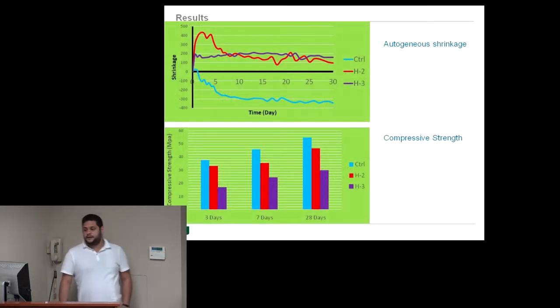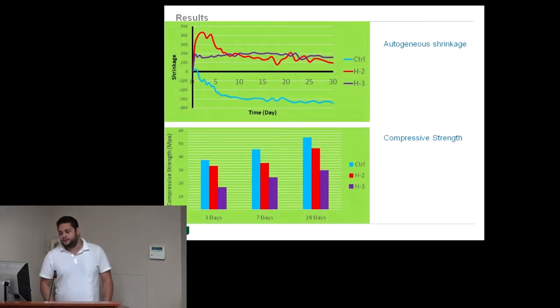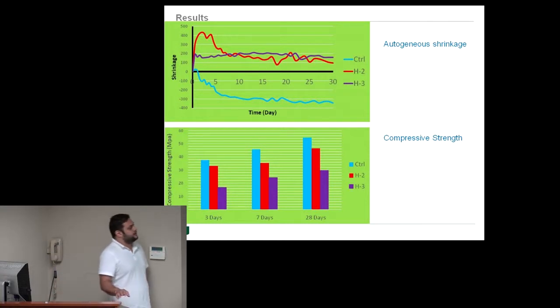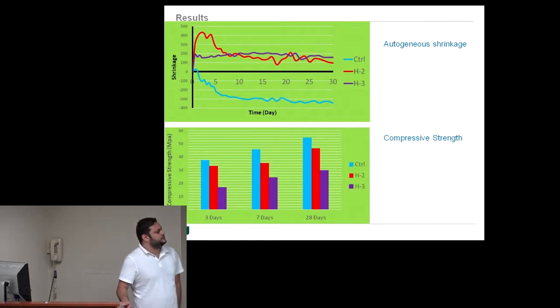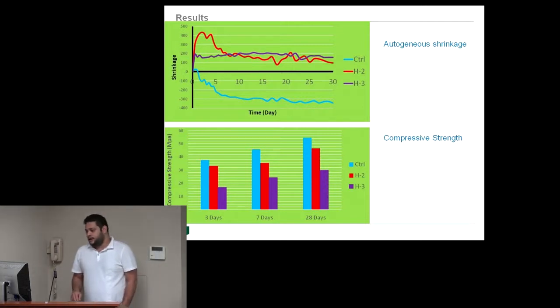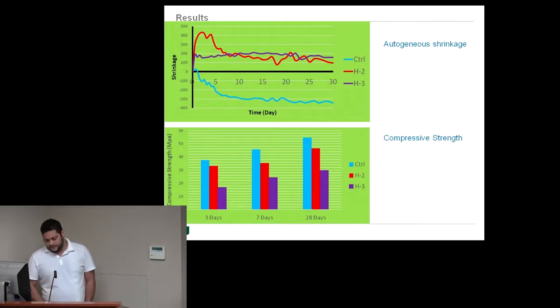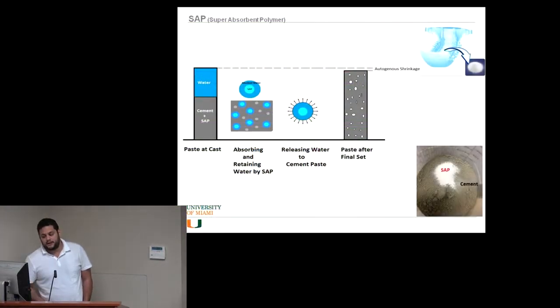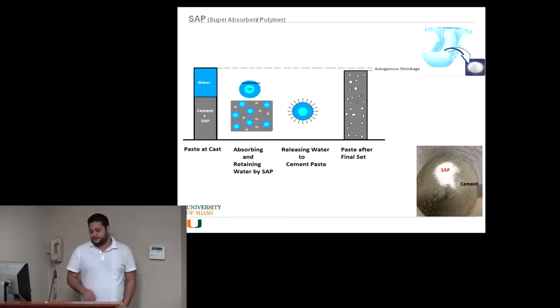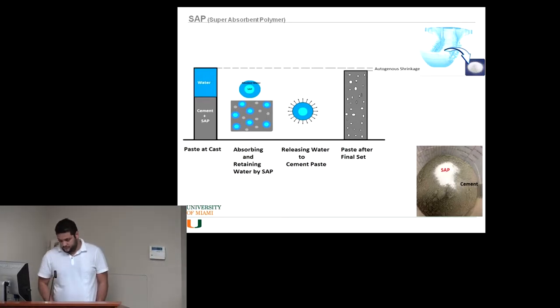So this is my result. I have already used two different kinds of SAP. As you can see in the first graph, the amount of autogenous shrinkage is mitigated using the hydrogel. But the problem with the hydrogel is that the compressive strength reduces because it leaves some voids inside the paste.